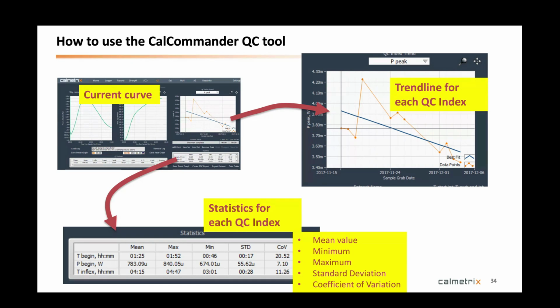Okay. And then I wanted to show you that, because here we have things where you have to trace a 24-hour curve and wait for 24 hours to actually get a result. The main reason is that even in an isothermal calorimeter, the repeatability is not good enough to do it quicker, because theoretically you could say that just with the aluminate peak you have in the beginning, the first 30 minutes, you should be able to see if there's a difference from one peak to another. But you don't get that level of repeatability, even in just a plain isothermal calorimeter, to be able to see in half an hour of reaction measurement if something has changed or not.